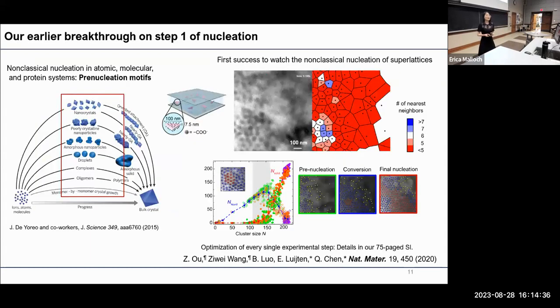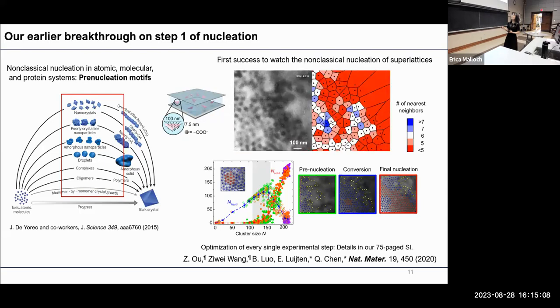So with all that established, the most important breakthrough in my pre-tenure work is the observation of the nucleation pathway of a nanoparticle lattice. Showing here in this schematic, we're able to load an aqueous suspension of nanoparticles into the liquid phase TEM chamber, and those nanoparticles are coated with charged thiols. Then we can induce crystallization by increasing the salt concentration in the system to screen the electrostatic repulsion. That's how we get the liquid phase TEM movie shown here.